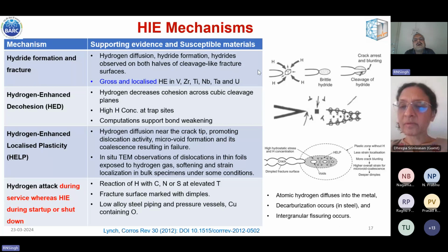So those who are doing testing in hydrogen atmosphere should be aware of the pressure composition isotherm for the hydrogen and metal or alloy system. If you want to see the effect of hydrogen embrittlement, you should ensure that the partial pressure of hydrogen is more than the plateau pressure. For different systems, this pressure composition isotherm is available in literature. One can start from there. And since in case of zirconium, I just said that hydrogen does not come out, that is another concern.